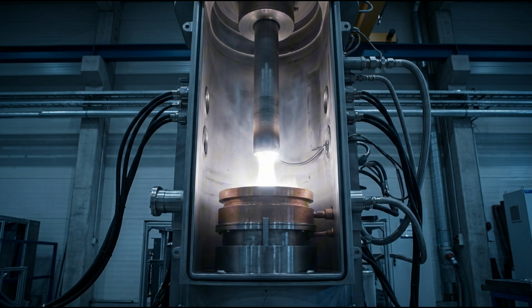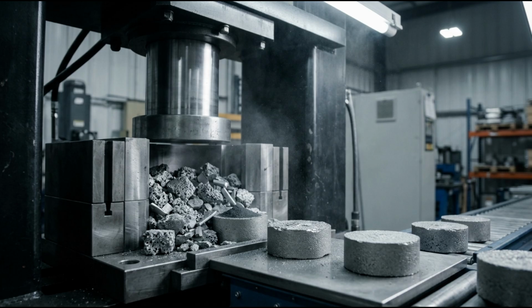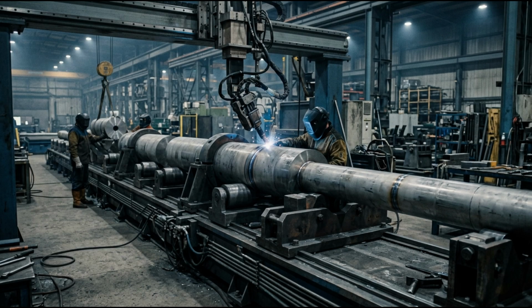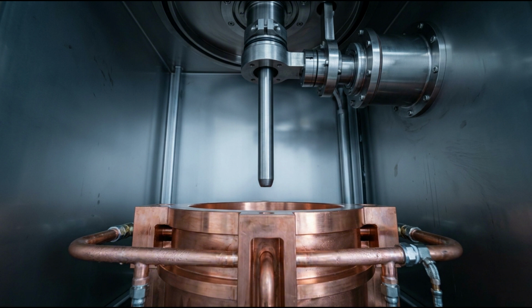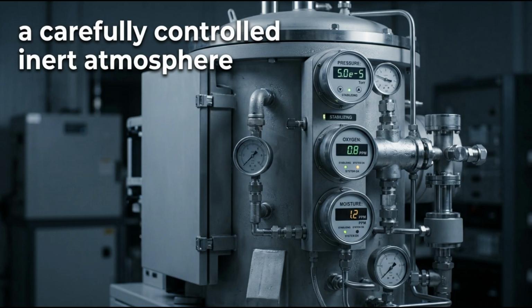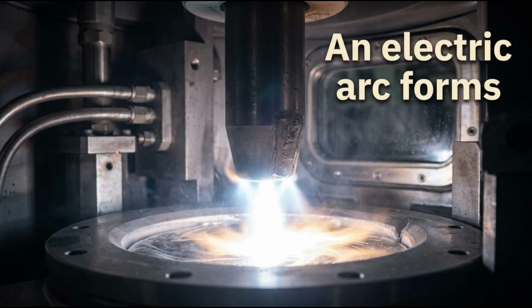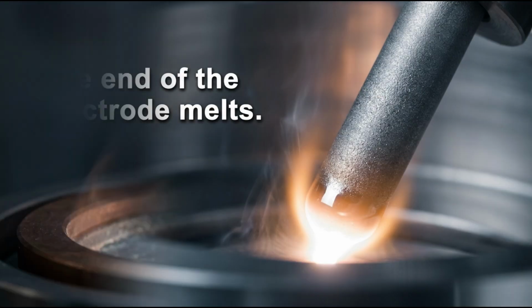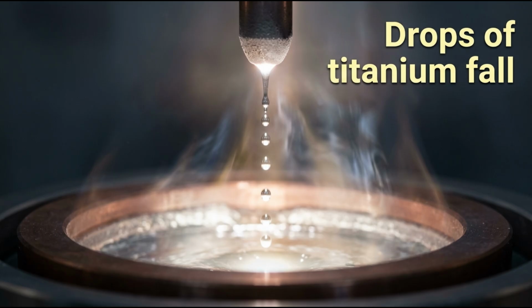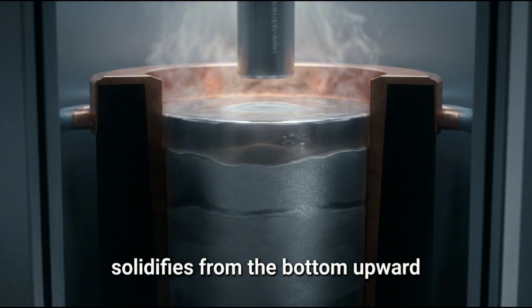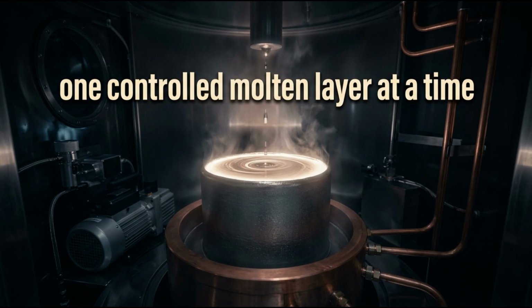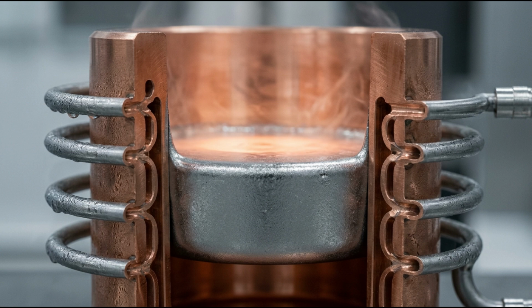Titanium sponge, suitable recycled titanium scrap, and measured alloying additions are pressed into compact shapes. Those pieces are assembled into a long, consumable electrode. The electrode is placed inside a sealed chamber above a water-cooled copper crucible. The chamber operates under vacuum or a carefully controlled inert atmosphere. An electric arc forms between the electrode and the metal below it. The end of the electrode melts. Drops of titanium fall into a molten pool inside the crucible. As the electrode is gradually consumed, the pool grows and solidifies from the bottom upward. The ingot builds itself one controlled molten layer at a time. The copper crucible is water-cooled, so the titanium freezes against it rather than reacting extensively with the container.